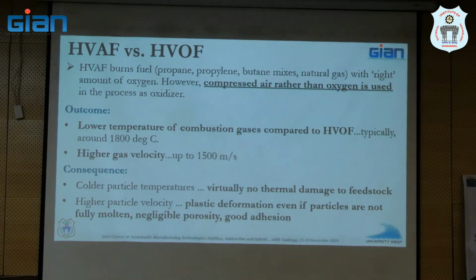So today, if we do an adhesion test, there is, by the way, an ASTM standard, C633-79. You coat a 1-inch button, and then glue it to another 1-inch button, and try and pull it apart in a UTM. The force at which you pull it apart is the bond strength or adhesion strength of the coating. That's how it's done. So when we do HVAF, we always get failure in the glue. There's no glue hard enough to overcome that bond strength. So we have come up with new ways of testing, like brazing, to be able to do that test. It gives you excellent adhesion, almost no porosity and things like that.